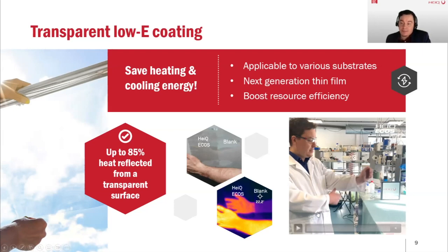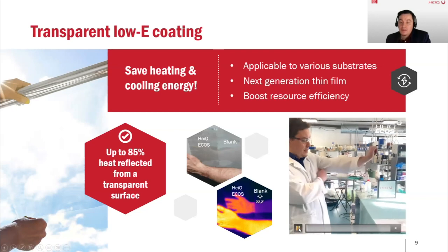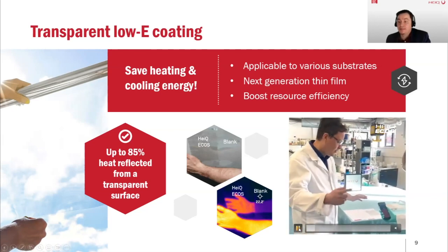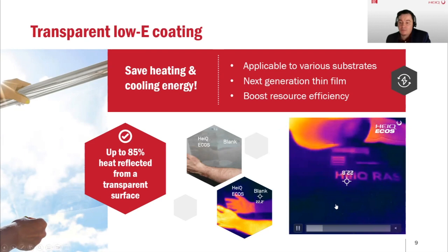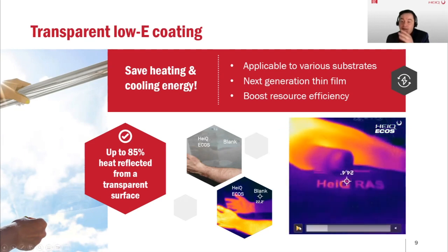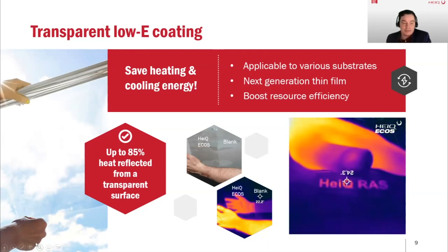And the same effect is shown in this short video. In this video, we printed the HeiQ RAS logo on a transparent substrate, and I'm holding my hand quite close to the surface, look at it with the heat camera, and you can see that the printed logo reflects the heat that is generated from the hand, and this can be detected in the heat camera. It's a visualization of the low E effect.